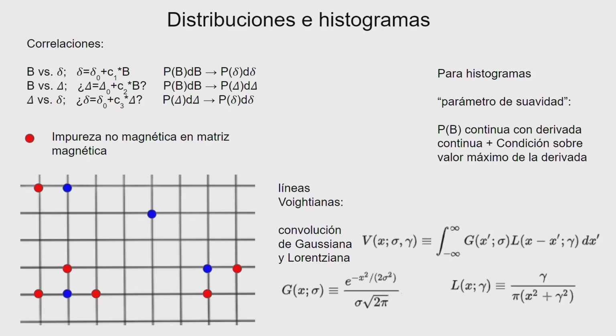But can we change the shape of the spectrum? Yeah, but the idea is asymmetry. The idea behind this situation, where you have a distribution of hyperfine fields, is that they are in different environments. That's the reason you have different hyperfine fields. So if you change from one hyperfine field to another one, you can think that your isomer shift changes too, while the surroundings don't change too much. And then you have to have a small correlation because some of the lines are so overlapped.